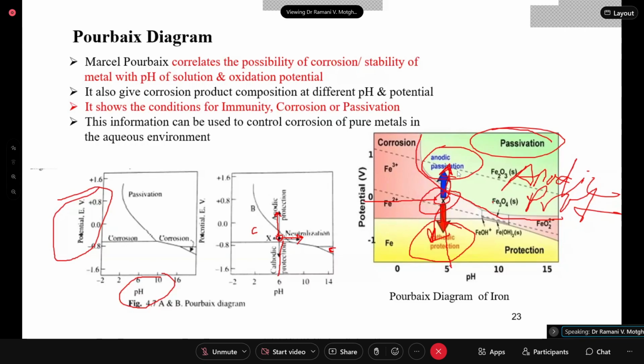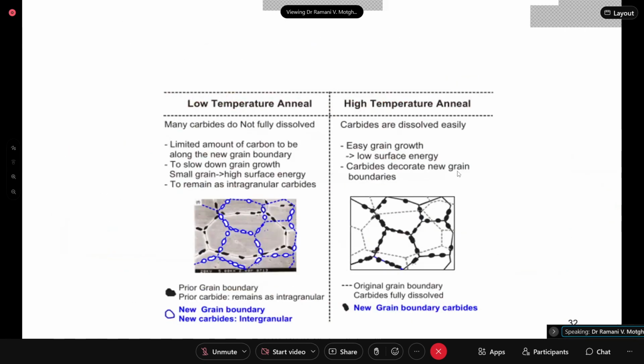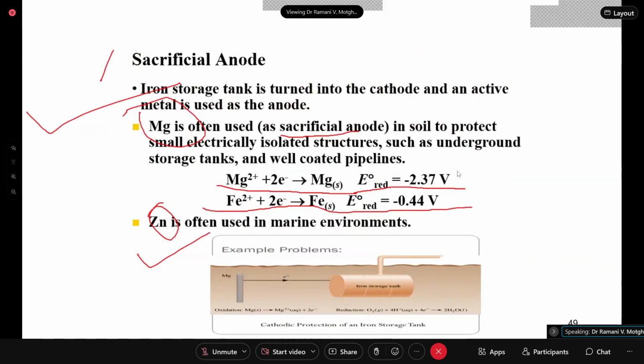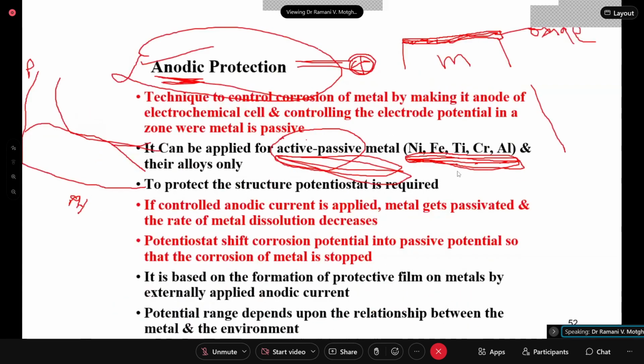This iron system is studied intensively for such phenomena: what is the potential and the effect of pH on the iron, whether it shows corrosive behavior, at what potential corrosion takes place, and that concept is used in anodic protection. In anodic protection, you use a potentiostat which has three terminals, connected to the tank to be protected. If controlled anodic current is applied, the metal gets passivated and the rate of metal dissolution decreases. The potentiostat shifts the corrosion potential into the passive potential so that the corrosion of metal is stopped. It is based on the formation of a protective film on the metals by externally applied anodic current. The potential range depends upon the relationship between the metal and the environment.